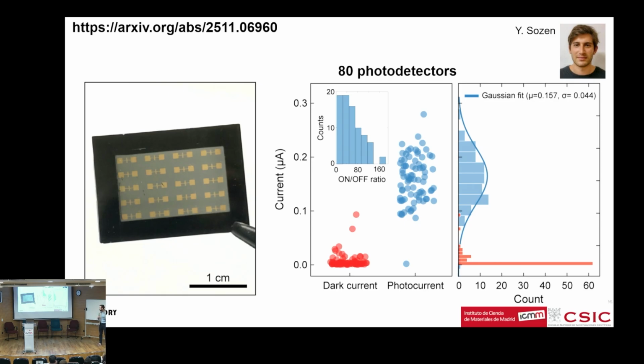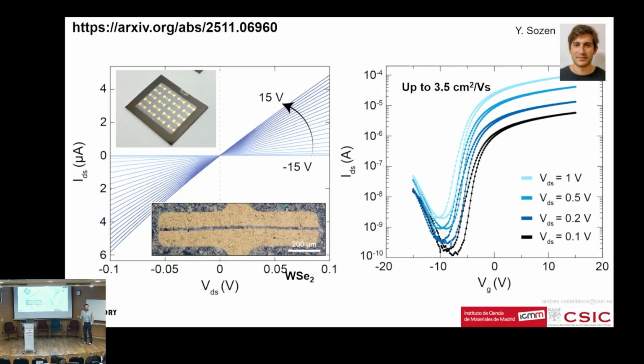Okay, so we have to always remember that the films that we produce here are just a network of interconnected flakes. We fabricated as well field effect transistors using a backgate geometry, so using silicon with silicon oxide as a dielectric, and then fabricating the transistor. And this is important because in many of the low-cost field effect transistor works, they only work well when you use ionic gating. Okay, so if you use backgating in inkjet printed, spray-coated films with two-dimensional materials, performance is, allow me to say, crap. Okay, so these are not the greatest field effect transistors ever, but getting a mobility in the champion device of around 3.5 centimeters squared per volt per second is already remarkable. So when you compare this with liquid phase exfoliation material, spray coated or inkjet printed or doctor blade, all these different production methods, this number is huge.